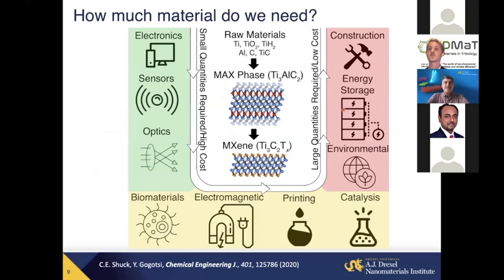I just praised the number of MXenes that can be made. There are actually already more than 200 two-dimensional materials reported. However, how many of them can be produced in amounts that would make their, for example, tribological or structural applications feasible? Just a couple. Those are probably graphite, graphene, boron nitride, molybdenum disulfide, tungsten disulfide, clay, a couple of oxides. All other materials are made in tiny amounts, often by CVD or PVD deposition in high vacuum here.